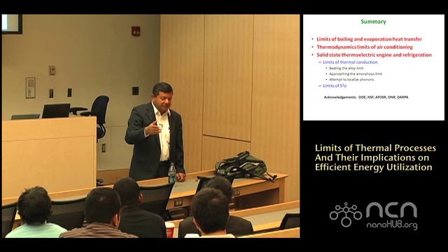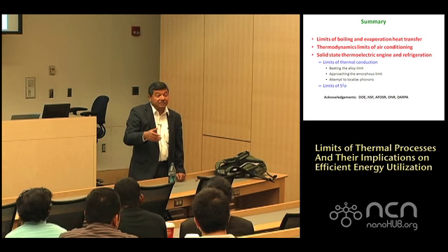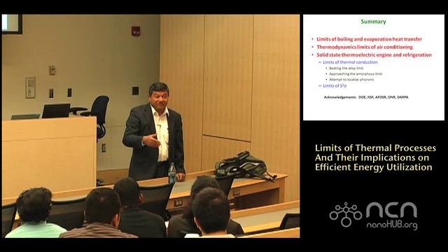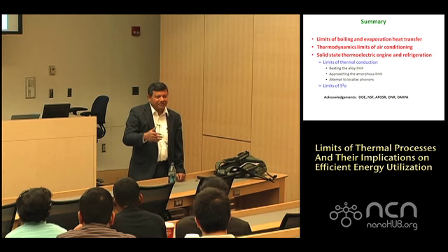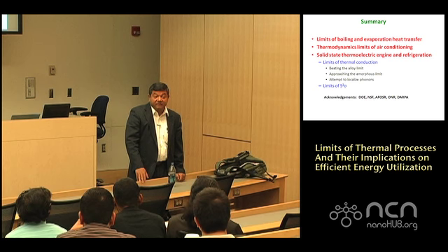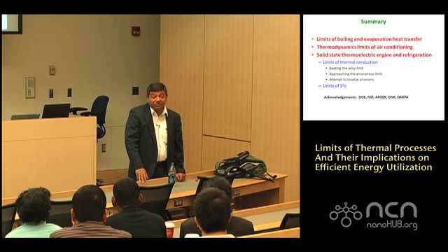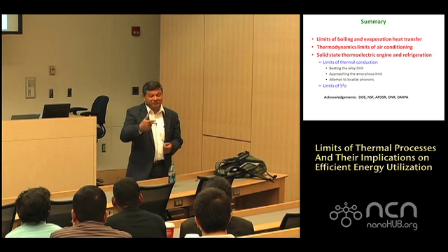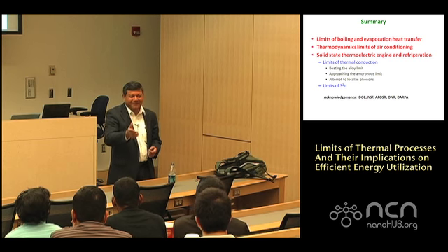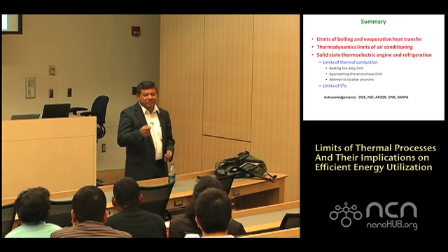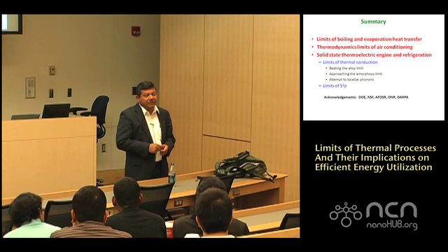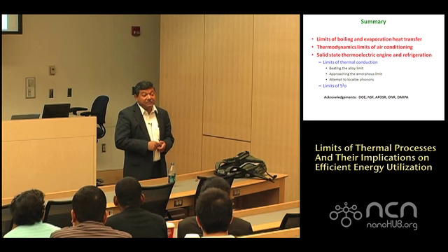I think you guys are looking at scandium nitride and gallium nitride or zirconium nitride, right? I won't say superlattice structure, it's a multilayer structure. I don't think it's crystalline, and that is showing some very interesting results. And there is an electronic contribution to thermal conductivity, I believe, that we cannot quite explain right now. We are measuring the thermal conductivity of your samples out here. I don't know who's growing them, but it's not quite explained totally yet. But it's very interesting. The power factor seems really good.